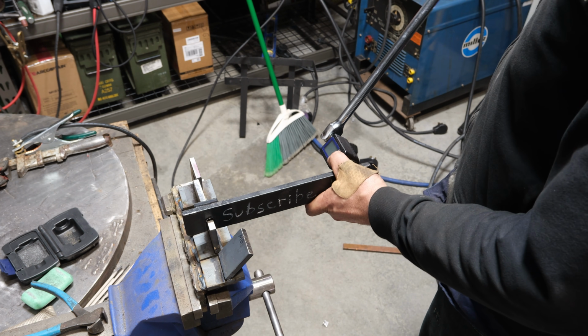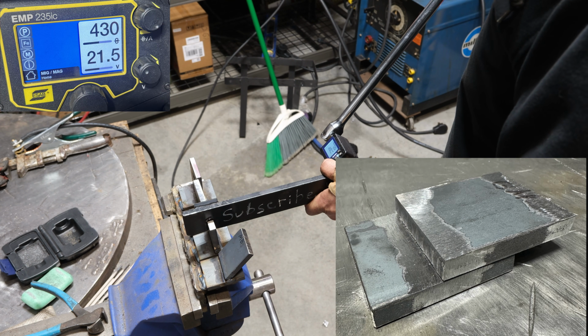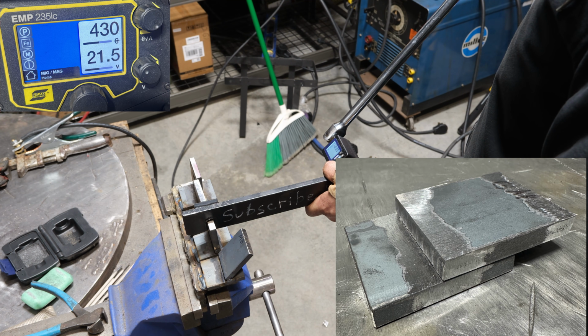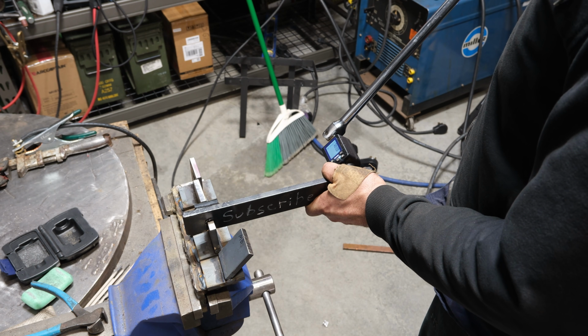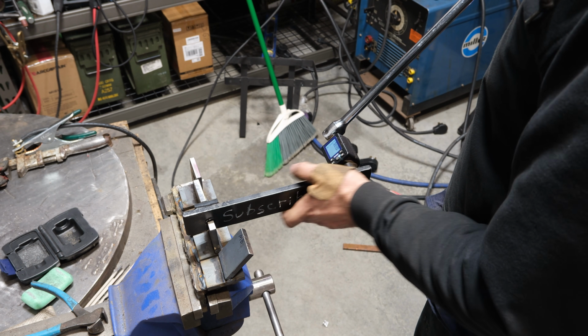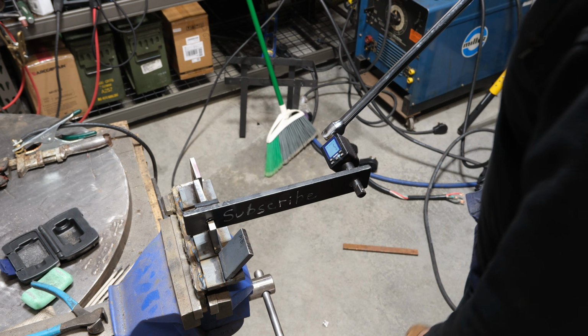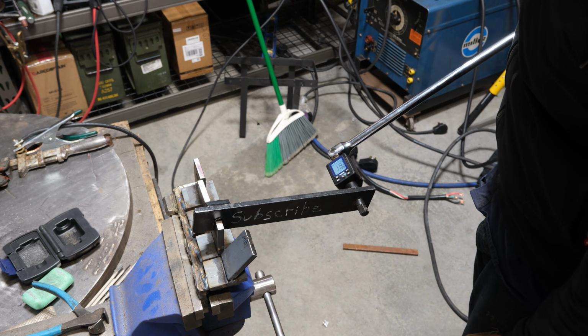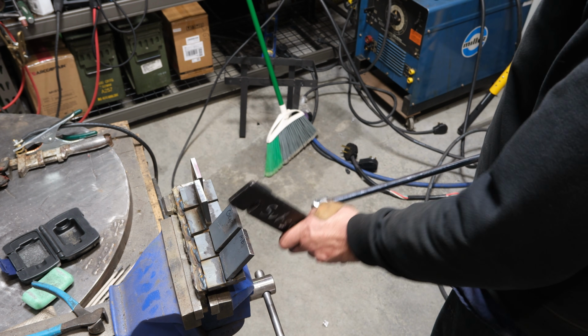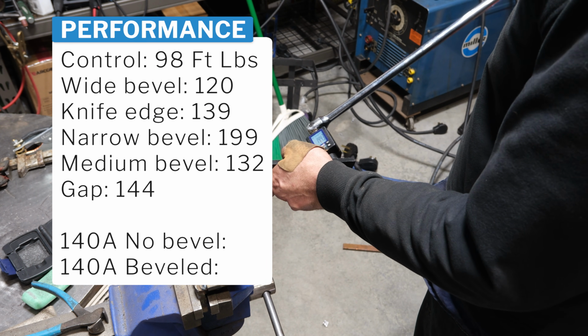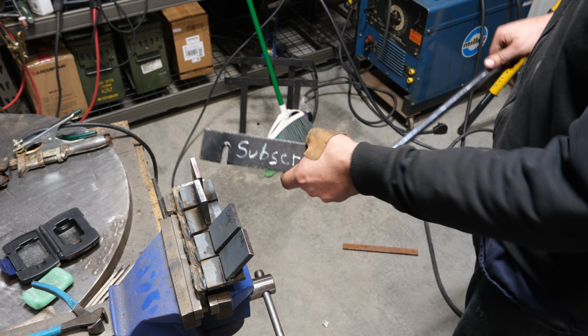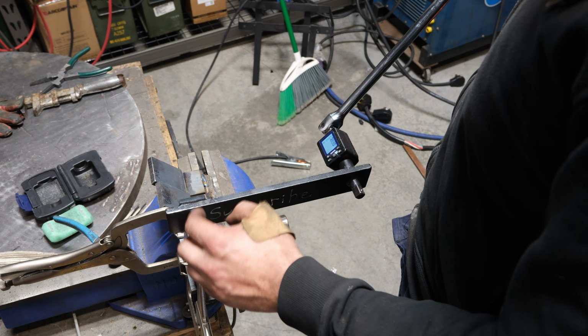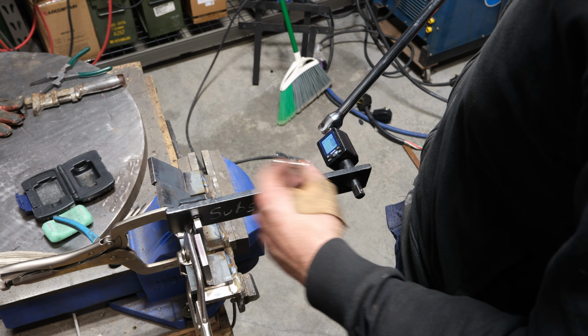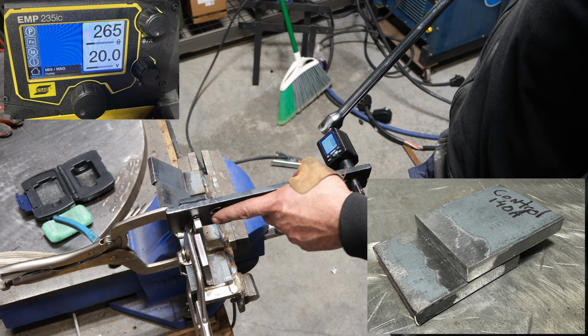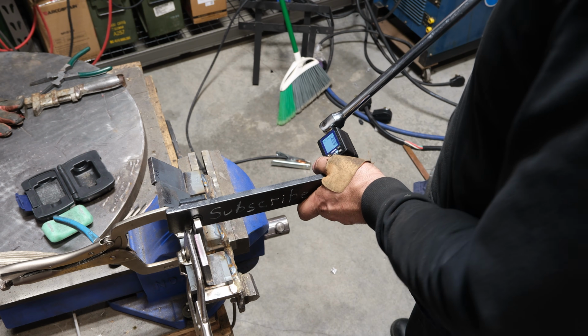Now this next one was welded with a gap rather than a bevel. So to put a number on it, I would say an 1/8 inch, maybe slightly like a 64th under, so an 1/8 inch, maybe a little bit less. 144.3, so not too bad there. Now I'm going to reverse this in the vise so we can bend that one. So I got this one set up and I have clamps on the back to keep it from bending forward. It should work. This is the control for a 140 amp MIG weld without a bevel.